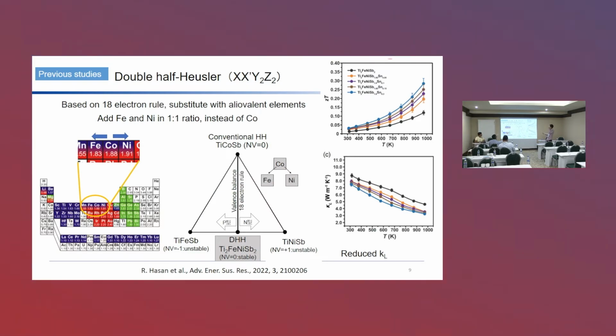There are some previous reports about double Half-Heuslers, where people are trying to make double Half-Heuslers based on titanium cobalt antimony. Here the cobalt is split into iron and nickel. Each of these two is not stable on its own, but if you make a double Half-Heusler composition, you can get the pure compounds.